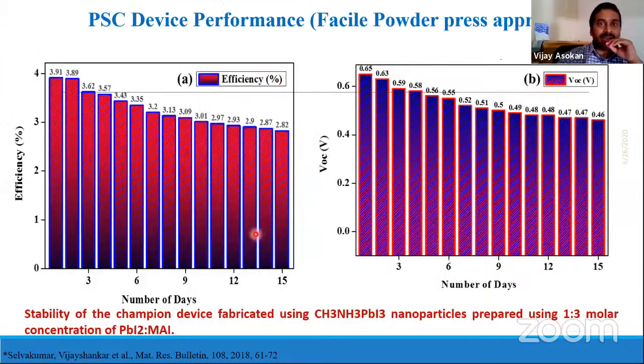Then even we have calculated such efficiency with respect to the time, because the degradation of perovskite materials with respect to time is more important to be considered. Of course, there are some loss of efficiency when it keeps on going on with different days. We at least calculated those things up to 15 days. Initially, we need to work more on those perspectives, considering the stability parameters in future.